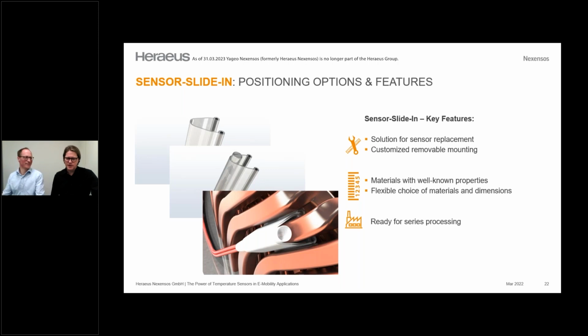But the question is really relevant because these materials are typically degrading in temperatures over 250, and then there is a discoloration with yellow and so on and so on. But all these tests are made with temperature spikes up to 250, and typically we made the long-term reliable tests in a temperature range up to 200 degrees.